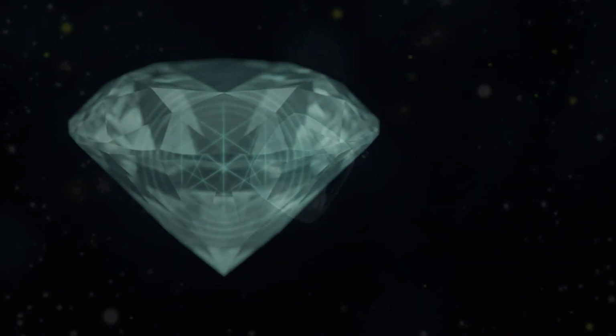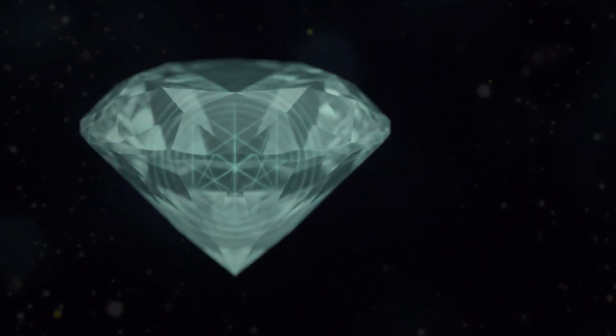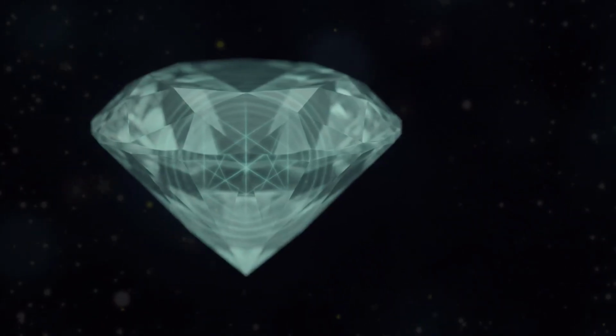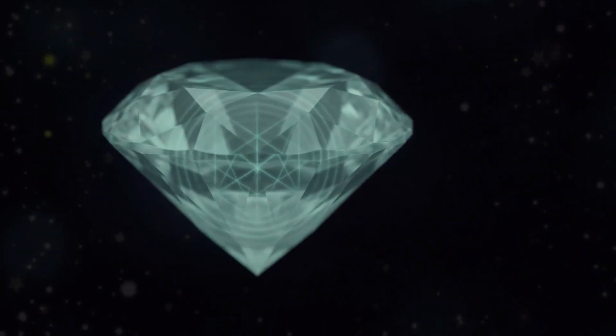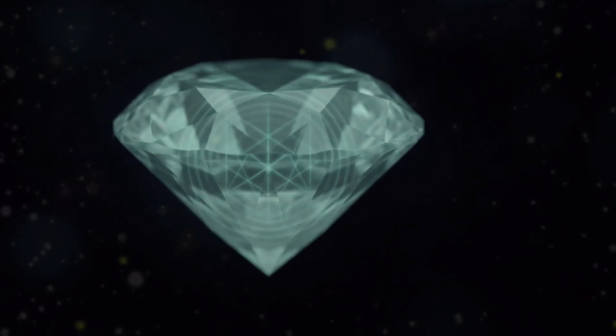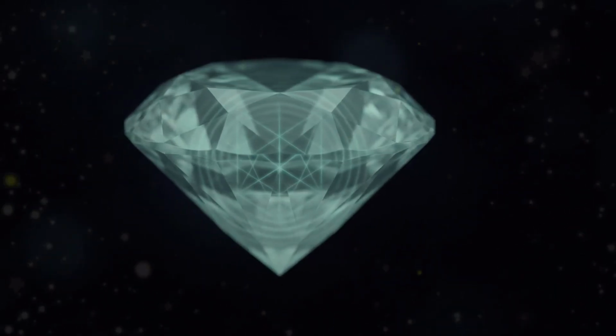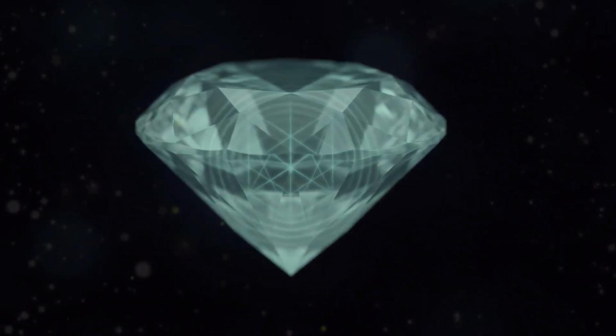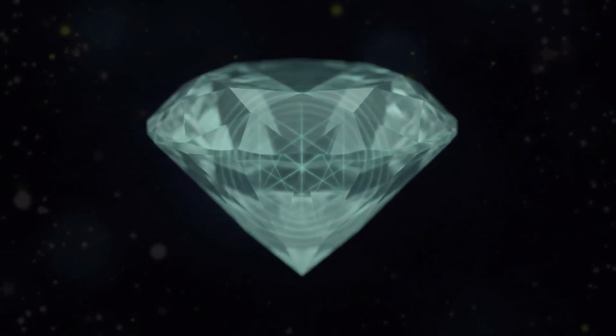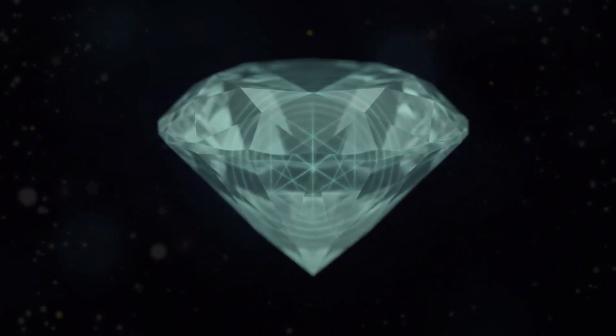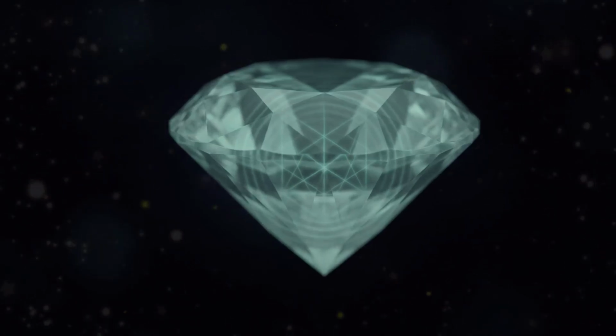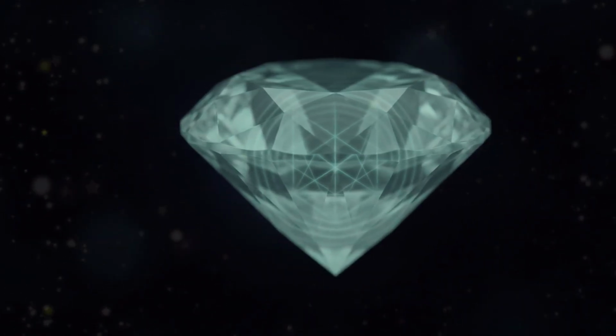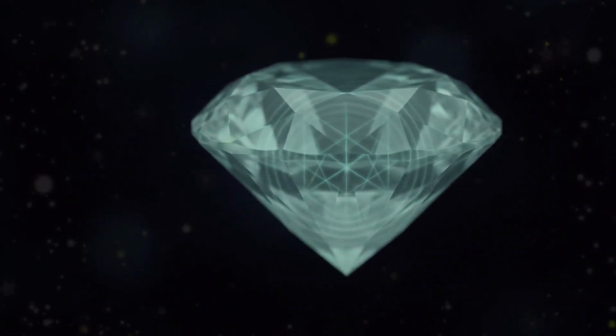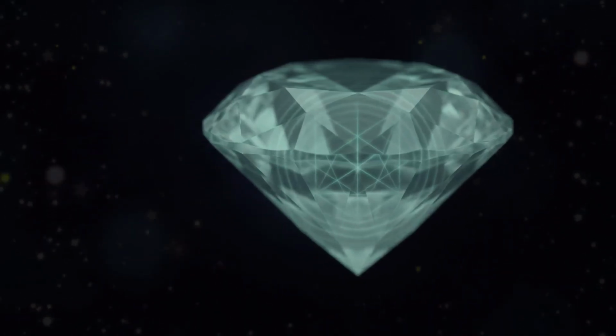Diamond holds a record in materials science. It possesses the highest thermal conductivity of any naturally occurring material, ranging from approximately 900 to 2,320 watts per meter per Kelvin, depending on purity and isotopic composition. This is a consequence of its crystal structure.